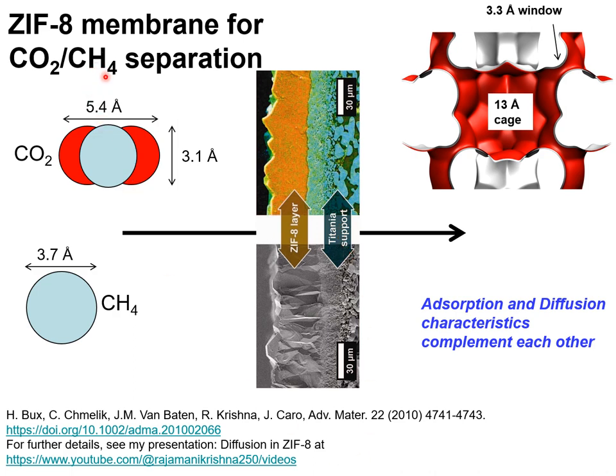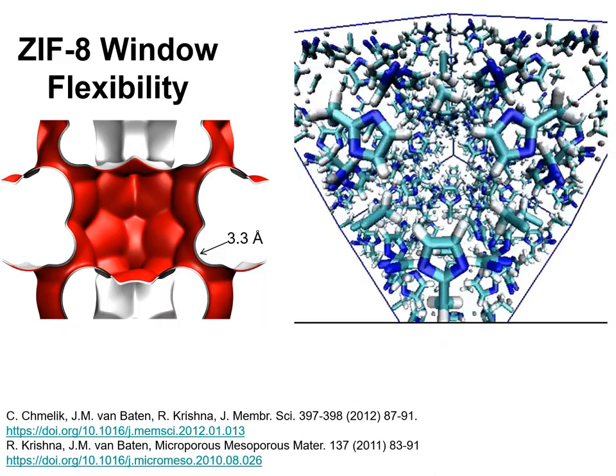ZIF-8 is a good choice for separation of mixtures of carbon dioxide/methane, carbon dioxide/hydrogen, and methane/hydrogen. An important advantage of ZIF-8 for CO2/methane separation is that both adsorption and diffusion complement each other, leading to high permeation selectivities in favor of carbon dioxide.